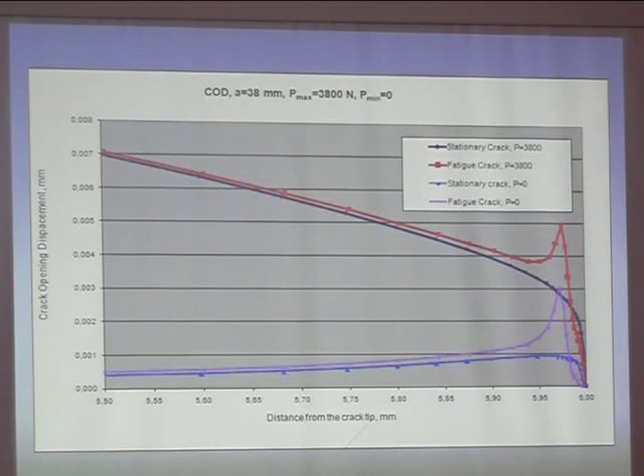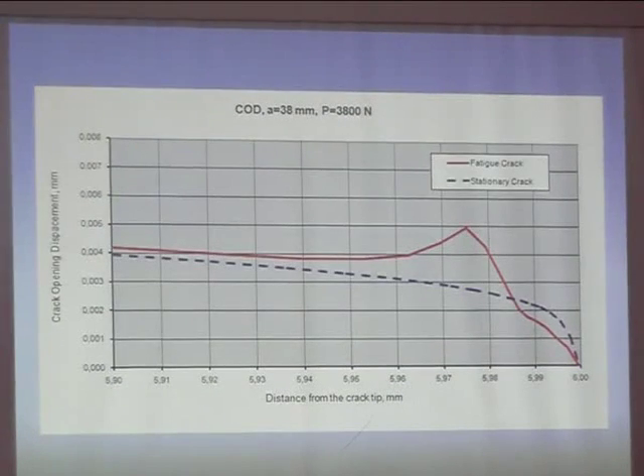So when we compare them, I zoom in a little bit on everything, and you see very clearly that this is the ideal crack without history, and this is the crack with history. There are two different displacement fields at the same K, the same crack length, everything the same. So if there are two different displacement fields, my conclusion is that there are two different stress intensity factors. Therefore, the history of the crack is affecting not only the minimum but the maximum as well. Whether we should take it into account later or not is disputable, but that's what I am finding, and this is in agreement with your experiments.